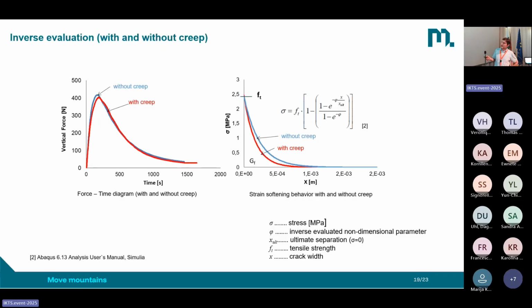If we now consider creep, because the sample is loaded at high temperature, during the test, creep will happen as well. And if we consider it in the simulation as well, then we see again, the fit is quite good, but the specific fracture energy determined with creep is significantly lower than in the case without creep. Why is this the case? Because the sample is deforming due to creep during the test. Creep is contributing to the area under the load displacement curve. So we need less additional work of fracture to fill the whole surface under the load displacement curve. And that's why this value with creep is lower than without creep.